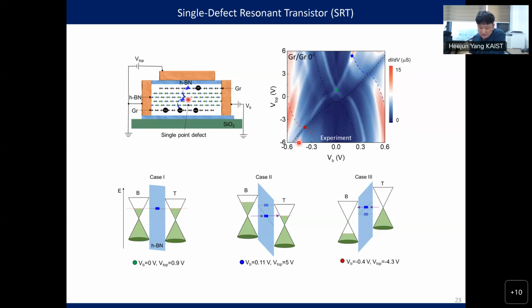Here we have bright lines. Actually, these bright lines happen because we have more efficient tunneling somehow. And then we know the origin. Here we have some defect state. And if tunneling happens via the defect state in the hBN, we have more efficient tunneling. That's what we see, the bright line.